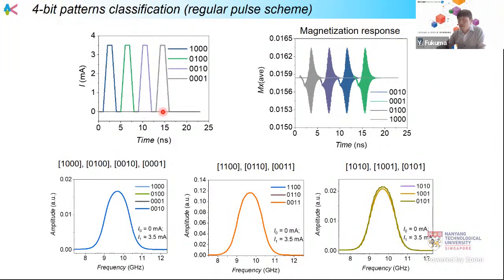The situation is similar for the third and fourth. Actually, we can see similar behavior for the different one-digit inputs. Of course, from this time domain data, by using the fast Fourier transform, we can get this kind of frequency domain spectra. Almost all the different inputs show similar behavior. Of course, when we put 2 ones as input, we can increase the amplitude of the precession. But there is actually no difference for 1 1 0 0, 0 1 1 0 or 0 0 1 1. If we separate the input 1 1, we cannot see a clear difference.